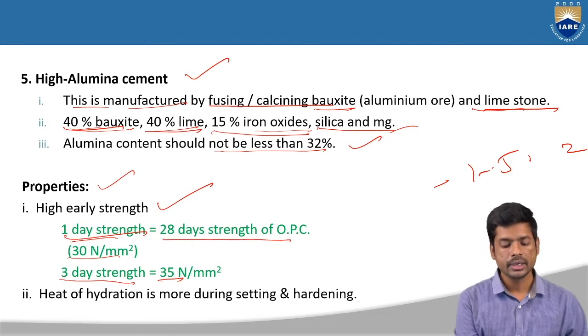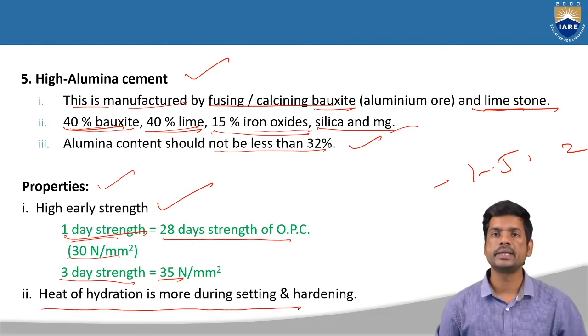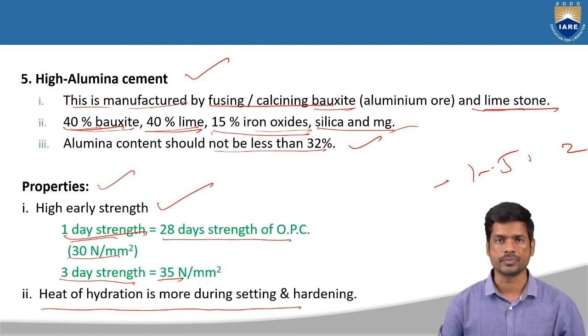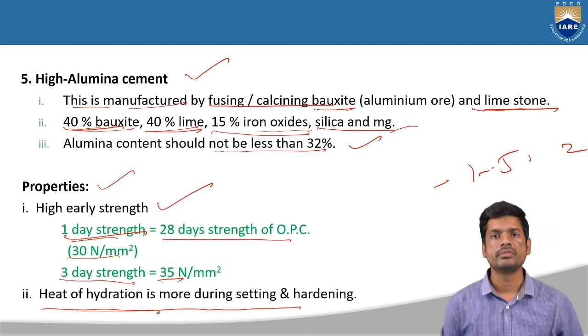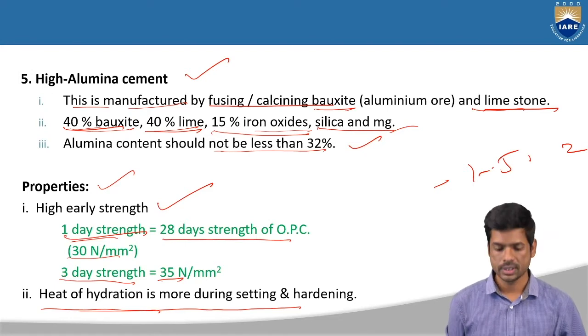Next, the heat of hydration is more during setting and hardening, because it achieves strength within a short time. If the strength is achieved very quickly, then the hydration process will be very rapid, and so the heat of hydration is also very high. It has to set and gain strength within a short time, which is why the heat of hydration is very high for high alumina cement.